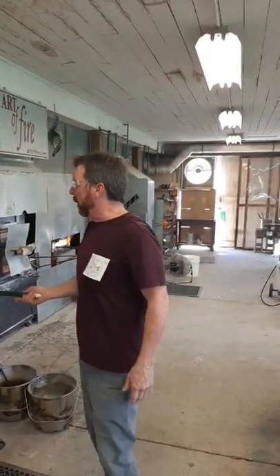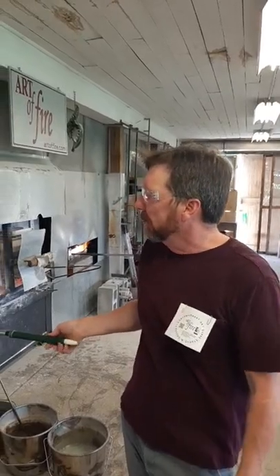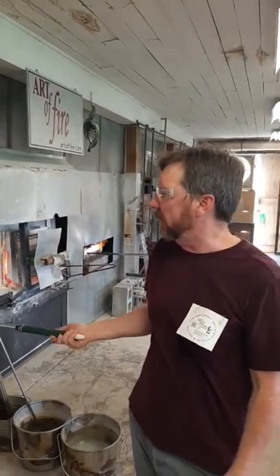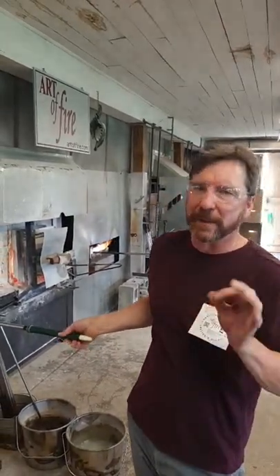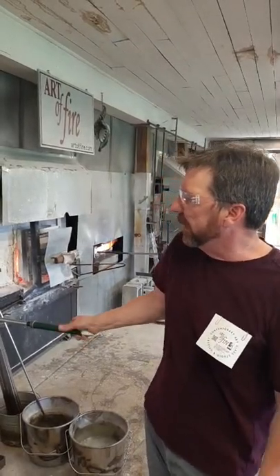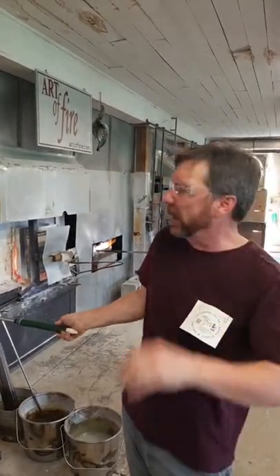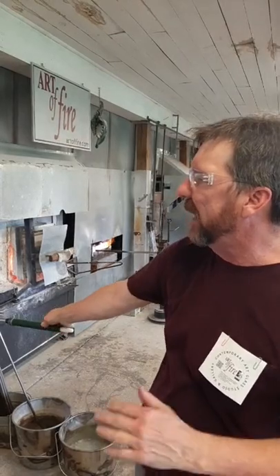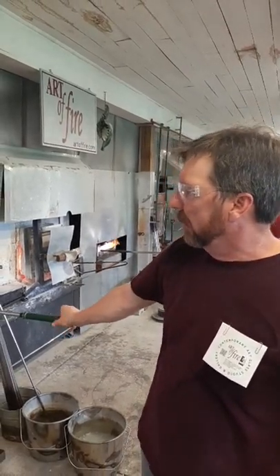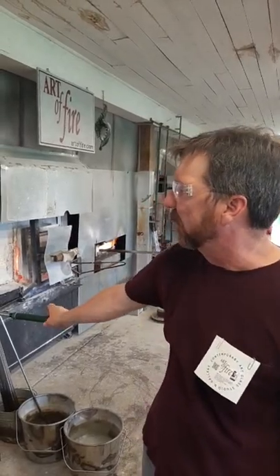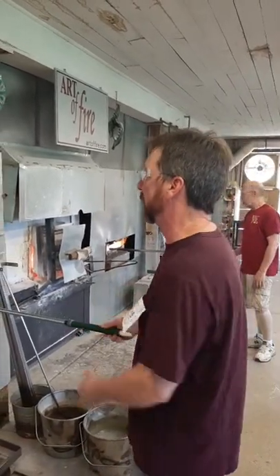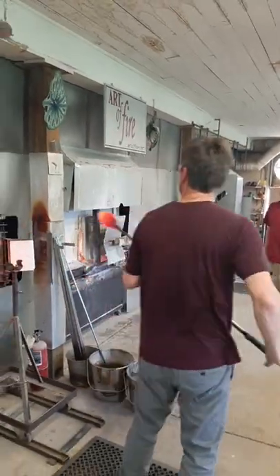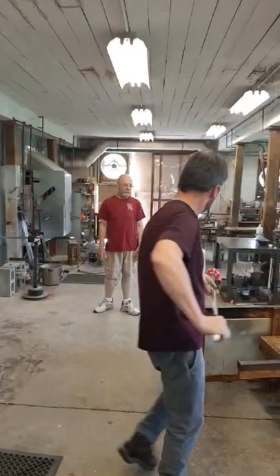So I'm going to fire polish this. This outer layer of clear glass rolling against the marver table got some chill marks, and sometimes that shows up as a little like haze between the layers of clear. That's really microscopic bubbles. So I'm going to fire polish. We're going to use a little bit of the surface tension of the glass to really smooth that surface out, let this cool. I'm going to air marver this in. I'm going to put another gather on that.